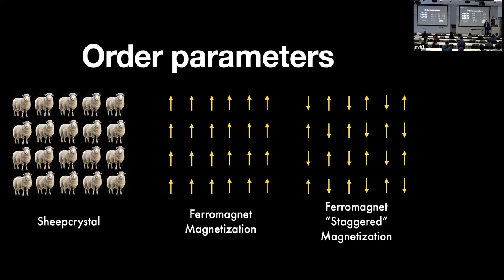Okay. Which brings me to the question of order parameters. So how do we characterize what the broken symmetry in the system is? Sometimes we invent a number that describes what that broken symmetry looks like, but most of the time it's actually a measurable property. So for example, in a ferromagnet, this is the kind of magnet that you have in a refrigerator, a useful order parameter would be the total magnetization in the system, what the dipolar moment of that magnetic material actually looks like. You could track that, and that would be a measure of how ordered your system is. And in the case of an antiferromagnet, it's what we sometimes call the staggered magnetization, which is sometimes measured as the difference between the magnetizations of the upspins in the system and the downspins in the system.